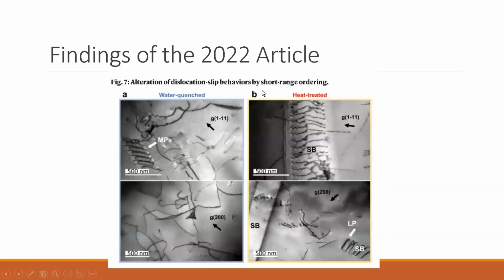And this short range ordering actually affects how dislocation slip in this material behaves. So it has an overall effect on the failing properties and the fracture mechanics of the material. So as a conclusion, what this article does is, previously the mixture and the orientation of the elements in the mixture was thought of as either random, or some theoretical models proposed that there might be some kind of ordering within the material.